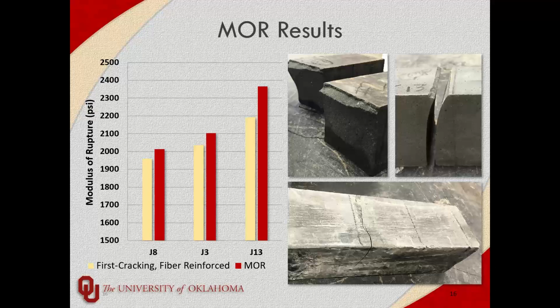Okay, and another question, how was the fiber distribution in the concrete mix? Did you get balling? No, oddly enough. I expected to, because we're around 2% fibers, which is a pretty common percentage. It's what Ductal uses. Ductal is a Lafarge-Holcim product. It's basically the gold standard for UHPC. But in any of our tests, and I actually cut a few cylinders open to see if we could see anything, we didn't notice any balling.